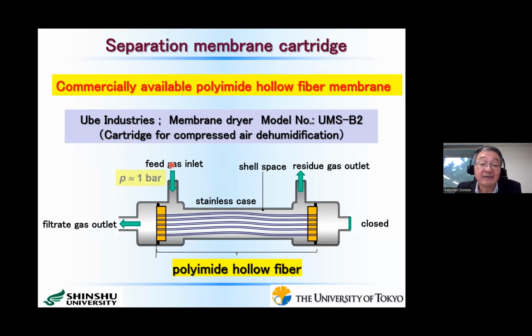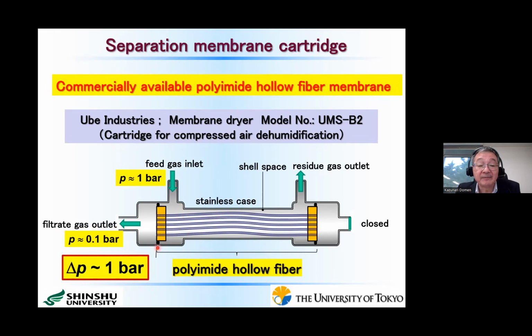So from here, we introduce the hydrogen and oxygen 2:1 mixture with saturated water vapor at a total pressure of about 1 bar into this one, and then it goes outside here. And we evacuate to about 0.1 bar. So through this hollow fiber membrane, the extracted hydrogen goes outside here. The total pressure difference across this membrane is about 1 bar, so we don't need to spend so much energy to separate hydrogen and oxygen.